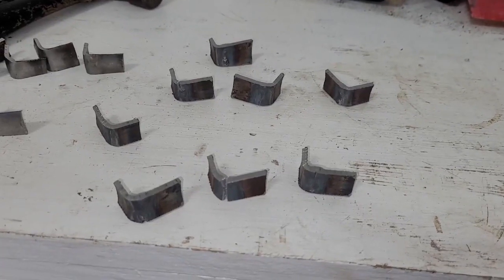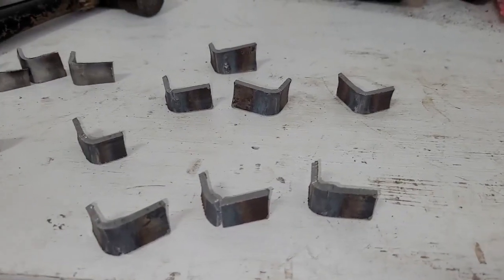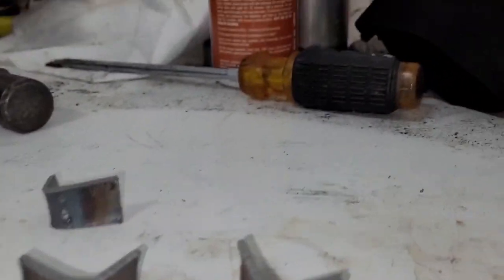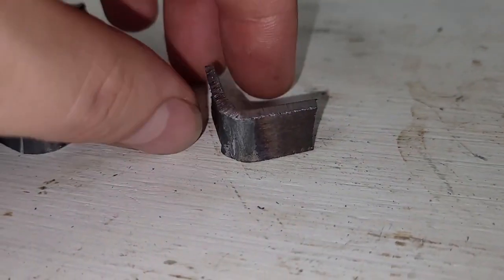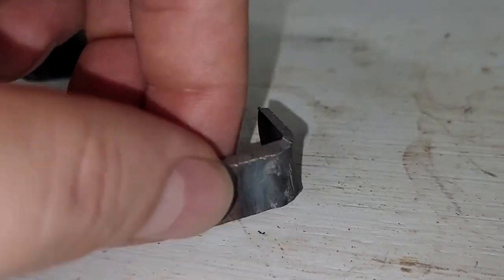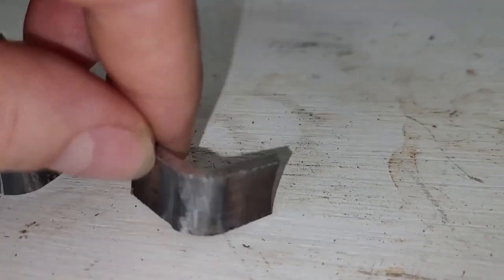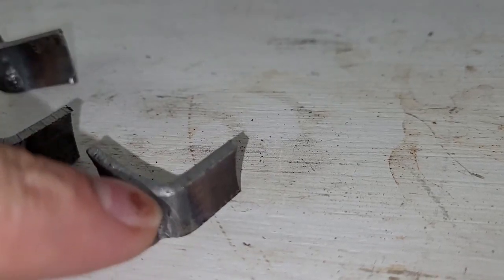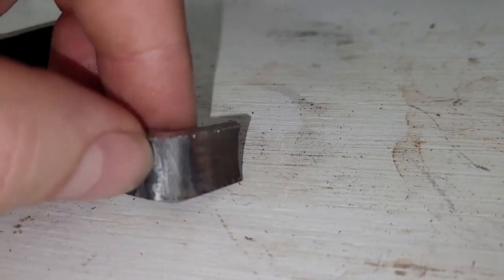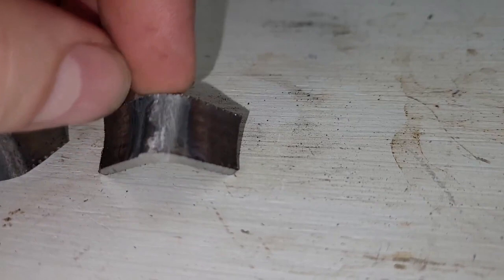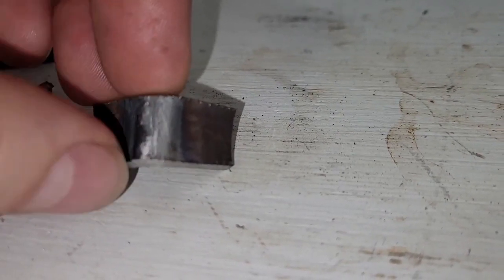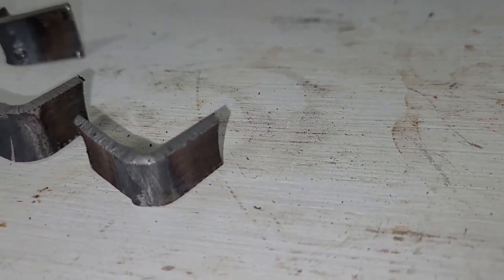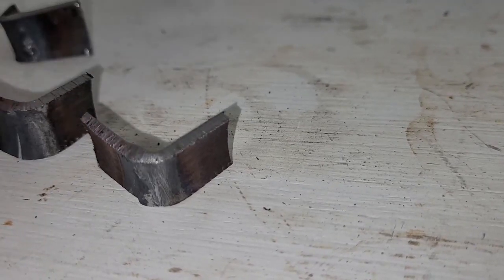Oh yeah, so a final note about our testing here. We are kind of making this more difficult on ourselves than we have to, and that's because these samples are curved, because I cut this out of tubing, so you can see there's a slight curve. And what that does is when you're bending it, you're really trying to stretch the edges. So basically we're trying to bend this to see if it cracks, but we're putting a huge amount of stress right on the edges, which are saw cut, not polished. It's a very big stress raiser.